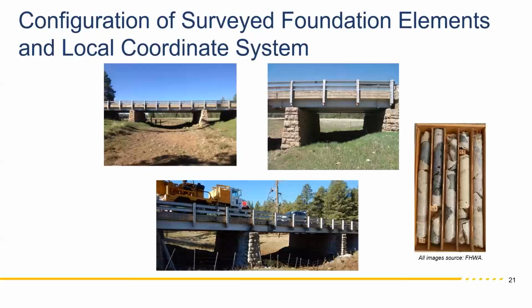So what we did is we cored from the deck all the way through the steel girders, all the way through the bedrock, through the foundations. We put a pair of cores in each of these foundation walls. And what was the coring cost? It was about $150 per linear foot. So a 50-foot coring costs us about $7,500, and a pair costs us about $15,000. So there's a way of doing that, and there are a lot of lessons learned, but they're very effective.